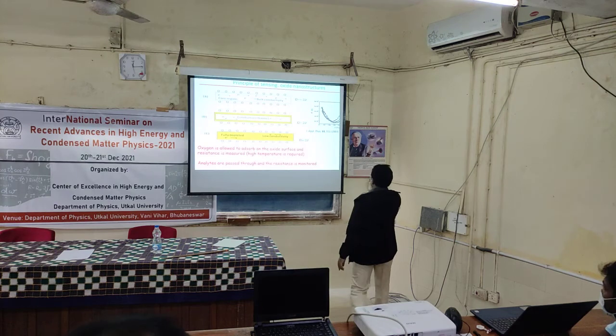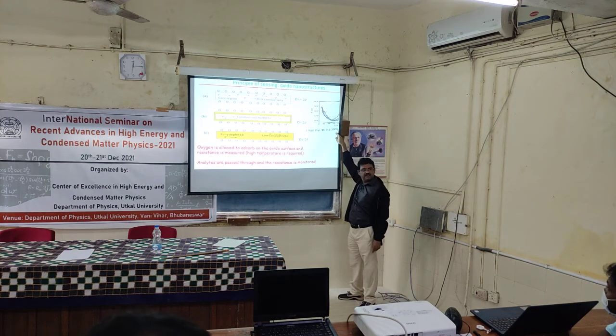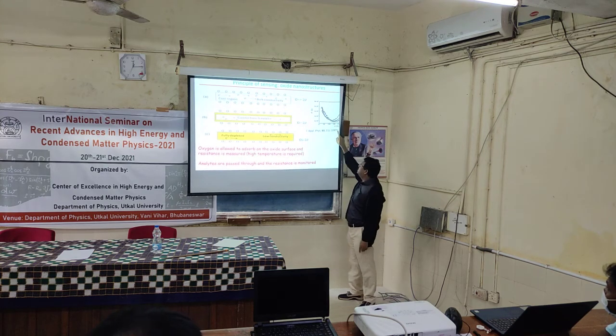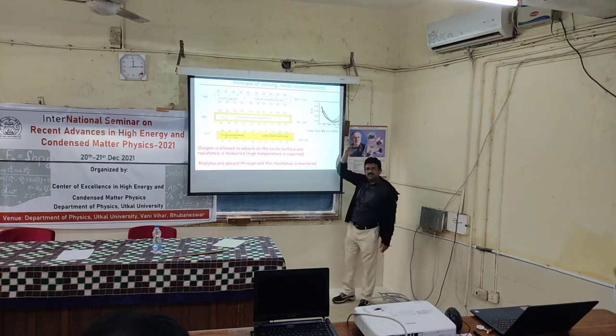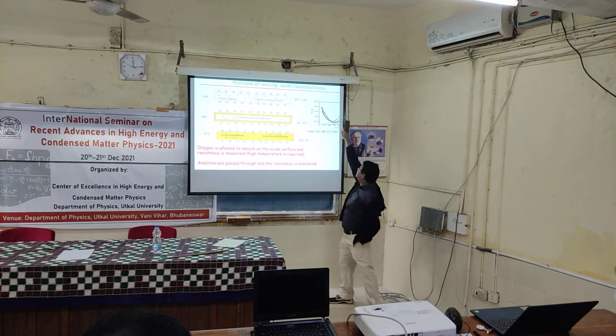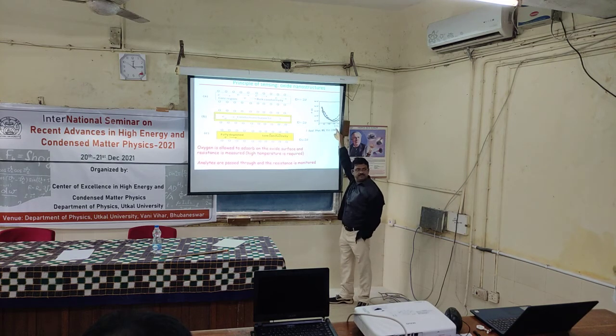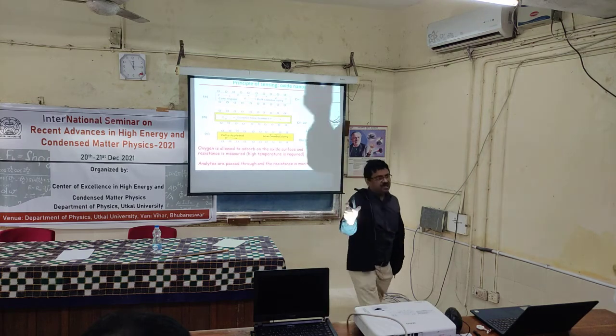So if I do this study without oxygen atmosphere beyond 200, I expect the resistance here because it is decreasing. And because of the oxygen I have this resistance. Now I pass the reducing gas. Once the reducing gas takes away the oxygen, giving back the electron to the tin oxide, the resistance will drop down here. And the change in the resistance gives you the indication of the concentration of the reducing gas.